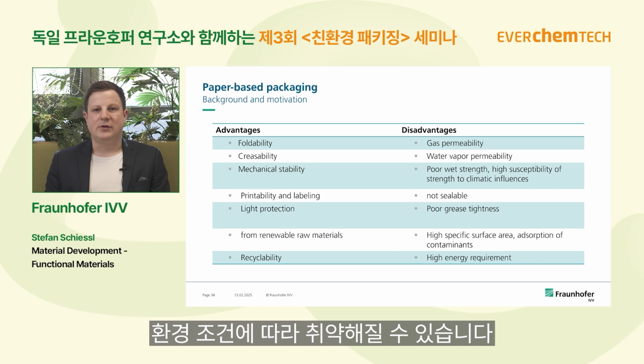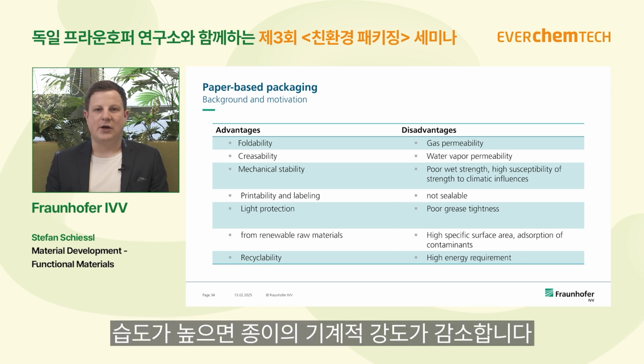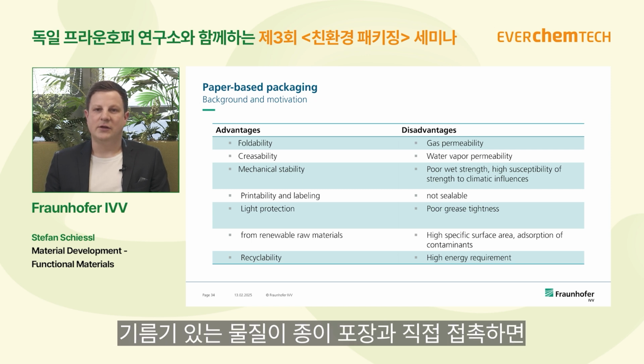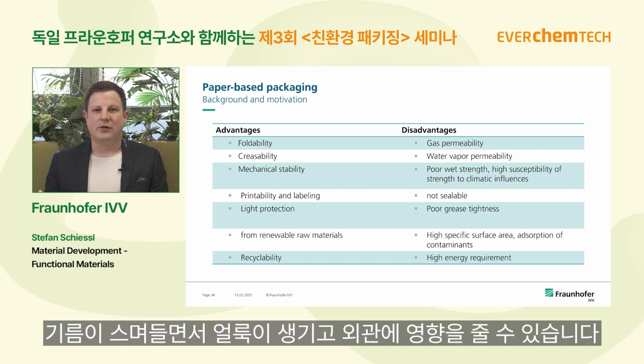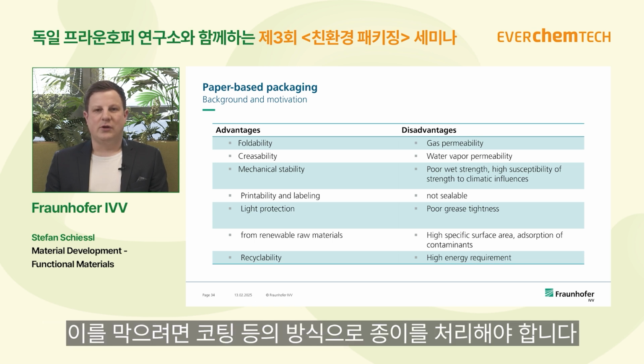Paper has a certain dependency on the environmental conditions, so if there is a high humidity, the mechanical strength of paper is decreasing. But there is also the problem that paper has no grease resistance, so if you have a fatty material to pack and it touches the paper, then the grease is permeating through the paper and gives some optical bad spots. So therefore we need to modify the paper by, for example, a coating.